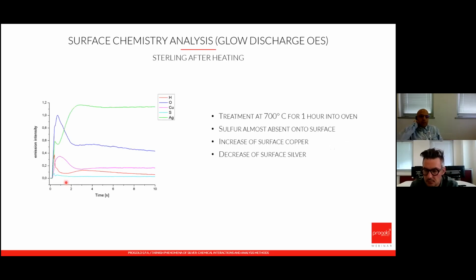On the other hand, the thermal treatment does not increase the surface sulfur so much, probably due to sulfide decomposition, as for roasting at high temperature in ore processing. But the development of copper oxide in the air is very visible. On the other hand, silver oxide is penalized because this compound is very unstable when heated. If I remember correctly, silver oxide starts to decompose around 200 degrees Celsius.